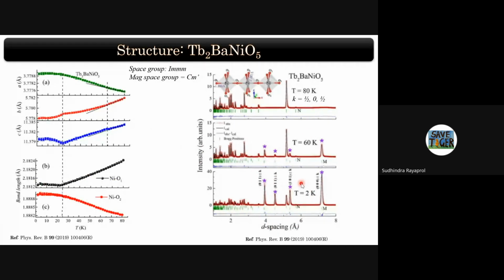But if you try to analyze the magnetic structure, we find that the magnetic space group is Cm', which is actually a polar space group, which actually allows ferroelectricity to be seen in this one. But the interesting point is that this space group is present from 60 Kelvin down to 2 Kelvin, which means there is no change in magnetic symmetry as we go down in temperature.